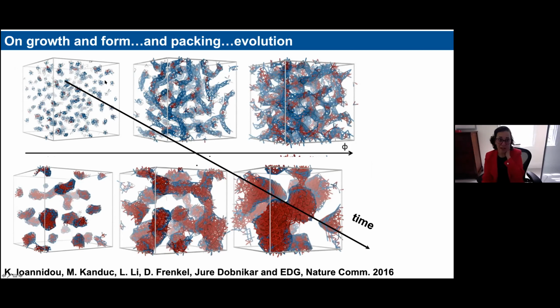And this is important. Why? Because I already told you that having these interactions in the beginning actually favors early stage percolation and development of mechanical strength and setting the pore size. Later stages, which are characterized by more and more attractive interaction, actually favor local densification of this network even more than what you would have if your interactions had remained the same. And this is very important because the fact that the material reaches such high strength, which is mainly captured by the contact between two nanoparticles, is really due to the fact that the material is able to densify continuously, even at much later times, and even when an already percolated solid structure is set.